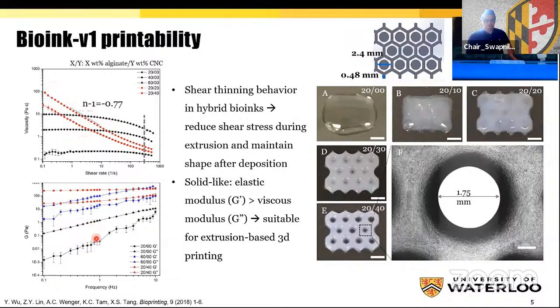In pure alginate, shown in black and blue, the elastic modulus is smaller than the viscous modulus, indicating that pure alginate, even at 6%, is liquid-like and not suitable for 3D printing. However, the elastic modulus is higher than the viscous modulus of the hybrid bioink, indicating more gel-like behavior. No crossover of G' and G'' at low frequencies means that the bioink possesses a permanent rigid gel network. To evaluate the printability of the ink, 5 formulations were studied.